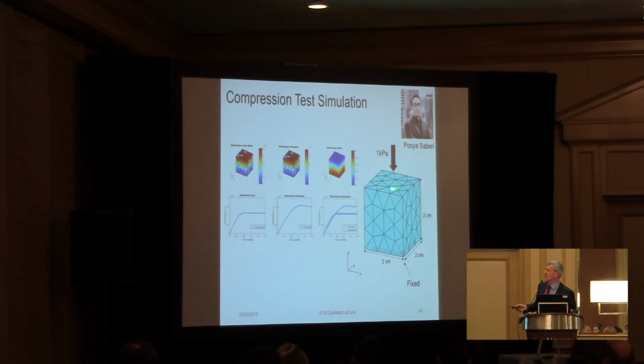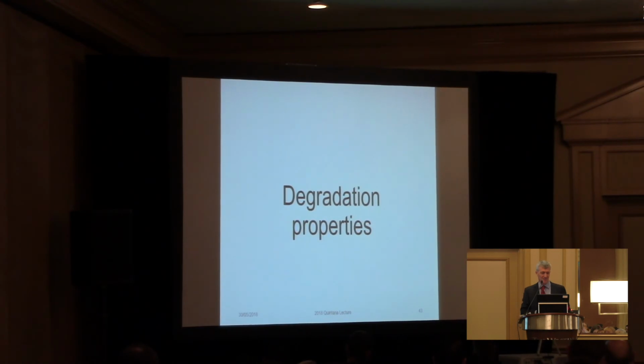And as you can see, if you put a force on a cube of material and you account for the electrochemical potentials and the fluid motions inside the organ, then you get that the volume distribution is not uniform, so you have changes in the density of the material, and you get that the stress-strain behavior is different because you have to account for the motion of the fluid inside. So think about this as when you squish the tomato, the juice flows out, basically. So you have fluid motion and mass change as a result of stress.